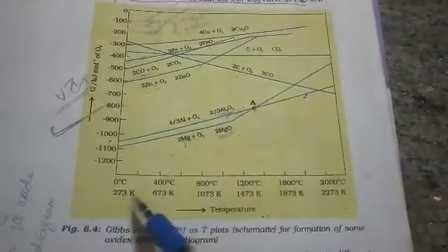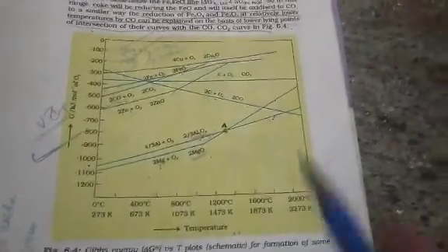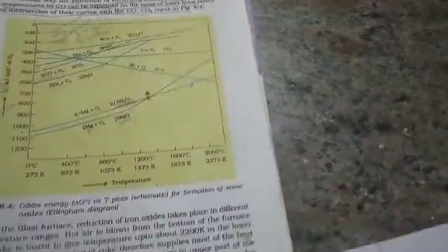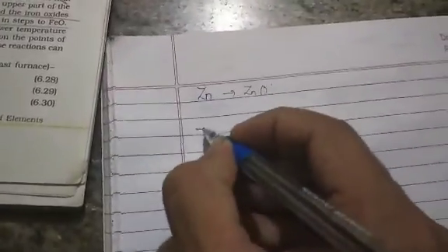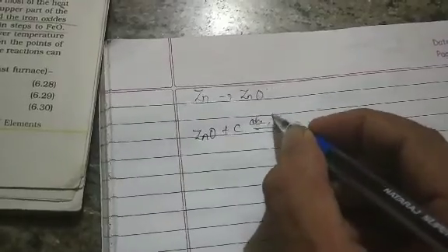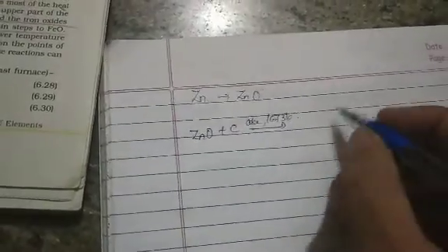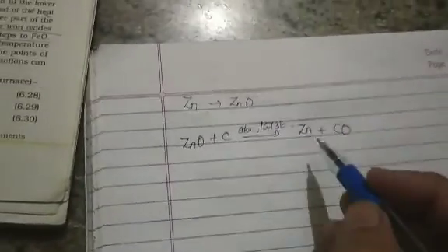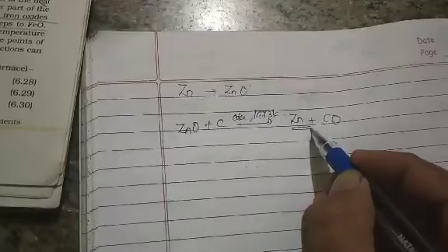So it is greater than that of the copper part, but we are also using coke itself as a reducing agent. For the purpose of heating, the oxide is made into briquettes, that is, a small powder-like material with coke and clay. You are going to mix it thoroughly. In that furnace itself, ZnO plus C, coke, at nearly 1673 Kelvin, you will be getting zinc plus CO. Whatever zinc you are getting over here is nearly in the molten form.